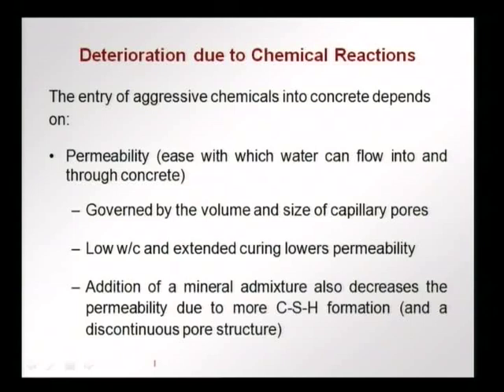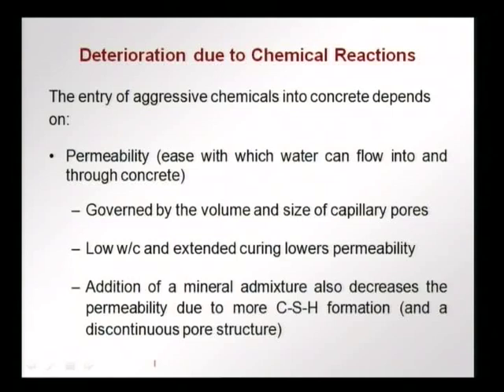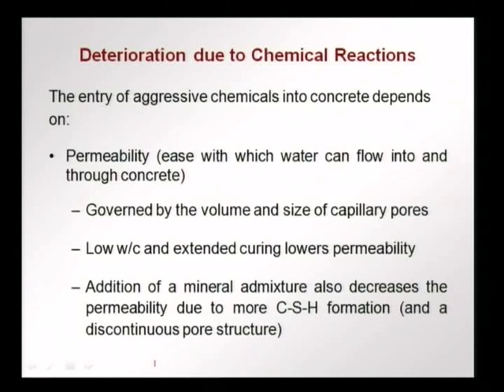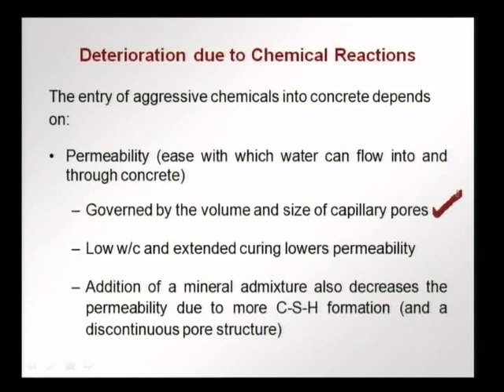When looking at chemical reactivity from aggressive chemicals entering concrete, the primary factor is permeability — the ease with which water can flow into and through the concrete. All of leaching, sulphate attack, and similar phenomena depend on water entering the concrete. Permeability is governed by the volume, size, and connectivity of the capillary pores. With very small, disconnected capillary pores, permeability is very low and the concrete becomes almost impermeable. Capillary pores can be decreased by reducing the water-cement ratio.